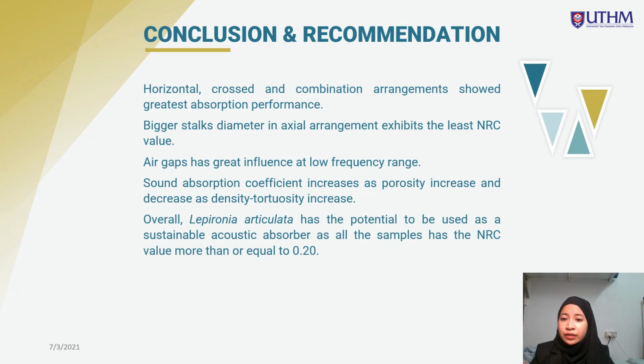In conclusion, the result revealed that the horizontal, cross and combination arrangements showed the greatest absorption performance compared to the axial arrangement. We can see that a bigger stalks diameter in axial arrangement exhibits the least NRC value. This is because when you use a bigger stalks diameter, there are fewer fibers in the samples. In addition, air gap has great influence at low frequency range. In terms of incorporating air gap, further increasing the air gap will reduce the absorption performance once the sample has achieved its maximum absorption at a certain thickness. Besides, we can see that the sound absorption coefficient increases as the porosity increases and decreases as the density and tortuosity increase. Overall, Lepironia articulata has the potential to be used as a sustainable acoustic absorber, as all the samples have an NRC value more than or equal to 0.2.